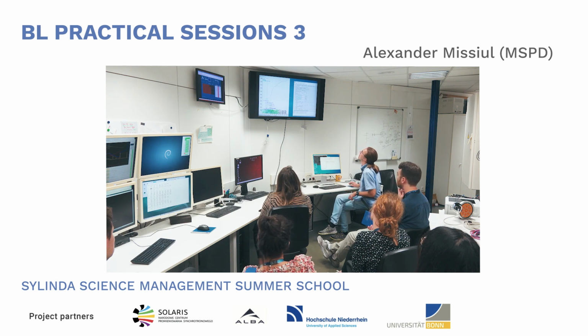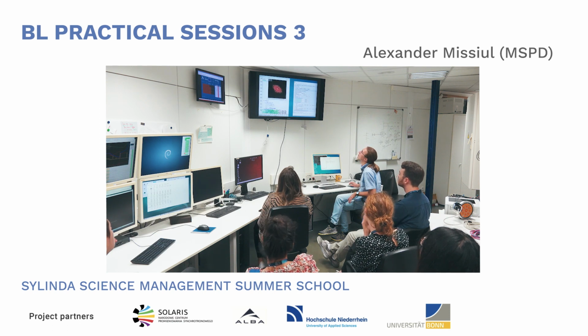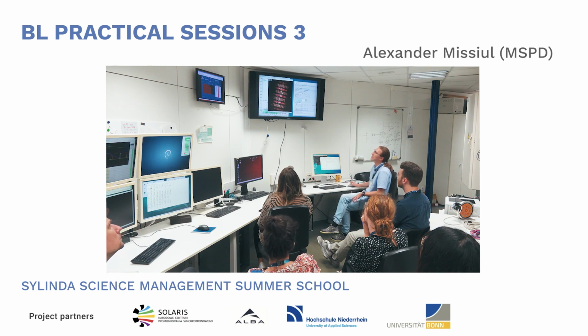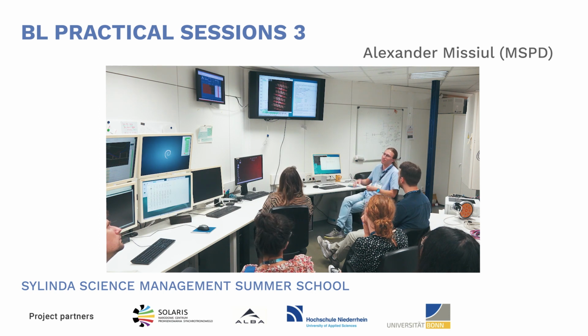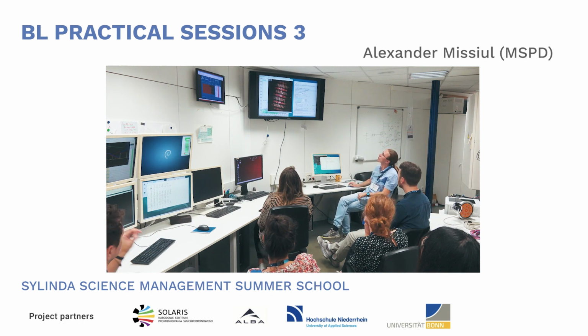So this is it, and I will put just some very random starting configuration. If we plot this configuration here, of course it is something completely wrong, basically because if the atom is in a general position, the symmetry elements create many equivalents, much more than really should be here. So we know that it should go to a special position, but let's see how it happens. So we create this optimization procedure. I tell it that I want to refine this crystal with respect to this diffraction pattern.